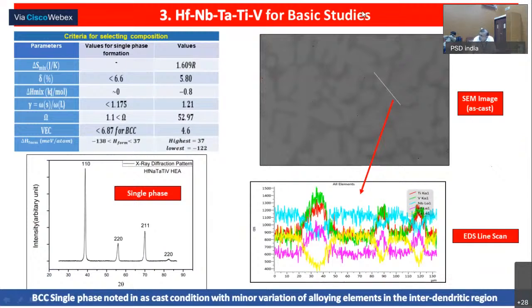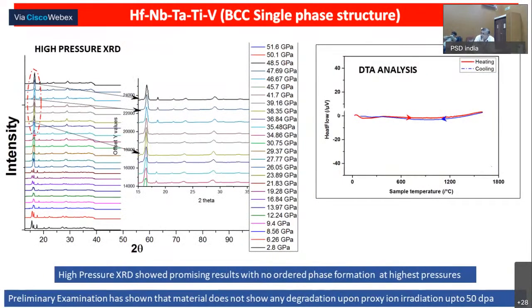If you examine the composition along this line, the phases have a tendency to segregate. There are certain elements which segregate on one phase, and another element which segregates on another phase. However, though compositionally the material shows two compositions, from a crystal structure point of view there is a single phase. And that is the point which is of very interest to all of us. So we started examining this phase a little extra to find out what is happening and why it is happening.